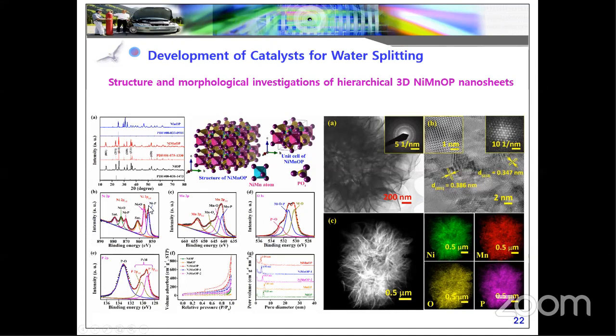You can see nickel, manganese, oxygen, and especially phosphorus; we get high binding energy. The metal binding energy is higher compared to the bulk nanoparticles, and the oxygen has metal-oxygen and P-O bonding. From the study, our material is confirmed by nickel-oxygen bonding, because of metal oxyphosphide, and the phosphorus-containing oxygen, this phosphorus oxide, further confirms the material contains oxyphosphide, because of metal oxyphosphide formation. And this material was further evaluated by TEM analysis.